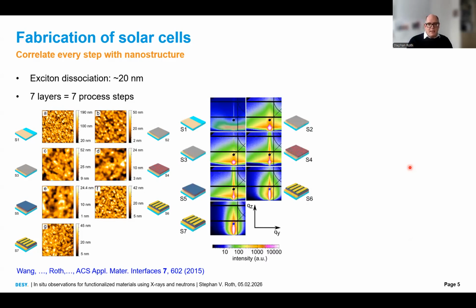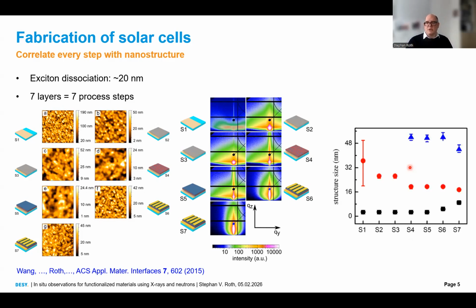And this is why in that example, 11 years ago, we used on each deposition step grazing incidence small angle X-ray scattering to check the length scales and how these length scales change. And you see here, indeed, when you deposit another layer on top of an underlying layer, these length scales change. And keeping in mind that we want to have a majority of the length scales in the active layer in this exciton dissociation diffusion length, you see this can become rather complicated, and therefore it's very important to look at the influence of processes on the nanostructure.